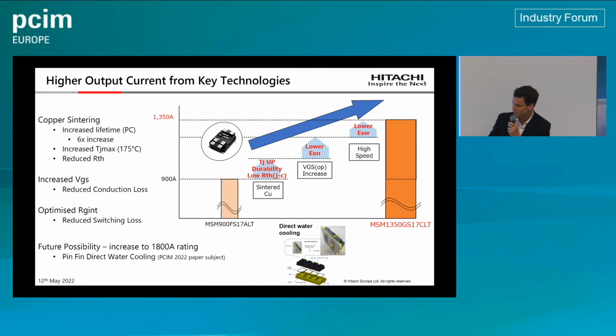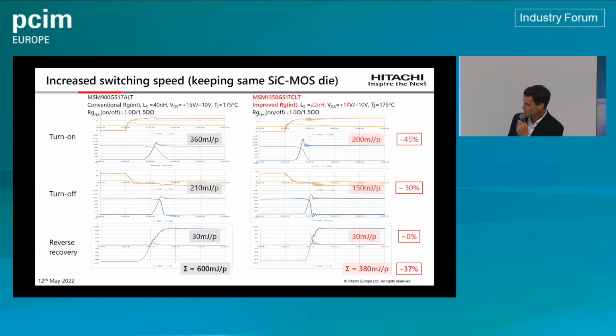We have a concept we're sharing at the moment where we could increase this further to 1,800 amps by applying a direct water-cooled pin-fin base plate to the module, allowing us to drastically reduce the thermal impedance and therefore drive substantially more power out of the module. So just to show this is real, we're sampling this product now to key customers. Here's some waveforms for it.